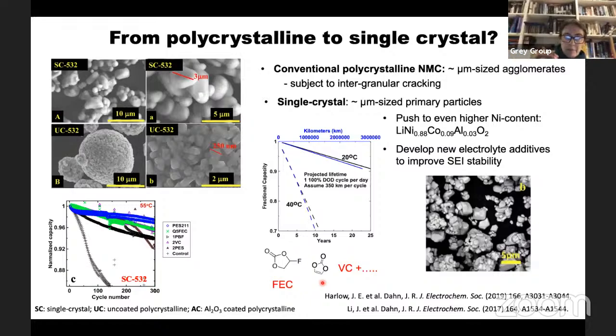So there are some interesting materials challenges. And so this is for the people doing material science in the audience. Originally, we started off with so-called single crystals, and they're not really single crystals. They're structures where the primary particles are just not agglomerated. And then new synthesis routes came along where we had these large so-called meatballs or raspberry structures, depending on which group you come from, made up of lots of small primary particles agglomerated to make these secondary particles. But when these particles are cycled, the materials expand and contract, and you get a lot of cracking. And so the push now is to try and do new syntheses so that you can make single crystal 811. And as a result, Jeff Dahn's group in Canada has come up with this battery that he predicts can last for years and years and years, if made out of these single crystals.